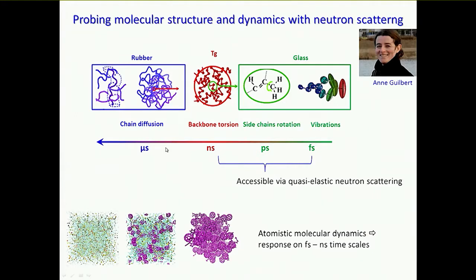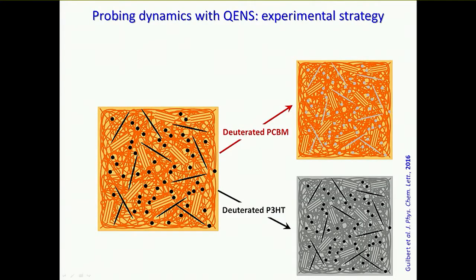We carried out a detailed study of the very well-studied binary system of poly-3-hexylthiophene and PCBM. Our strategy was this: with neutrons, you see hydrogen. If you want to look at one component and not the other, you deuterate the component you're not interested in, and then look at a blend which you hope will be more or less structurally identical to the hydrogenated version. So if we look at a blend with deuterated PCBM, we see the polymer. We look at a blend with deuterated P3HT, and then we can see the fullerene.